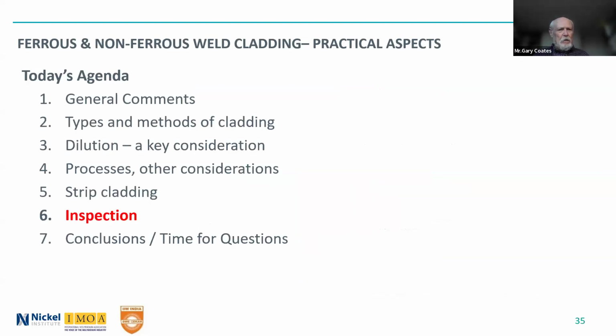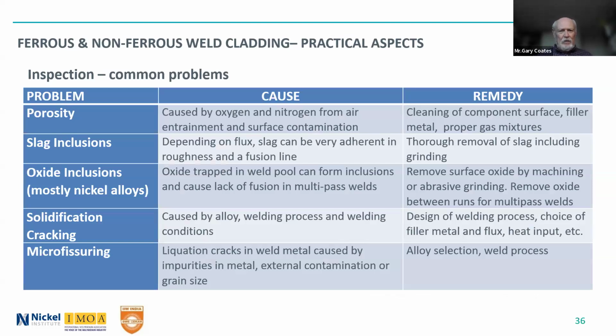Finally, just a few comments about the inspection, and you all are in the welding business. So you're familiar with the problems that can arise during welding, porosity, which can occur if the welding isn't done properly, or if the base metals are not properly cleaned, or contamination of the gas mixture. Where there is a flux, slag inclusions, you don't want them in the weld overlay layer. Oxide inclusions, it's mostly about nickel alloys, but you have to be more careful with nickel alloys than with stainless steels in this regard, in the cleaning between passes.